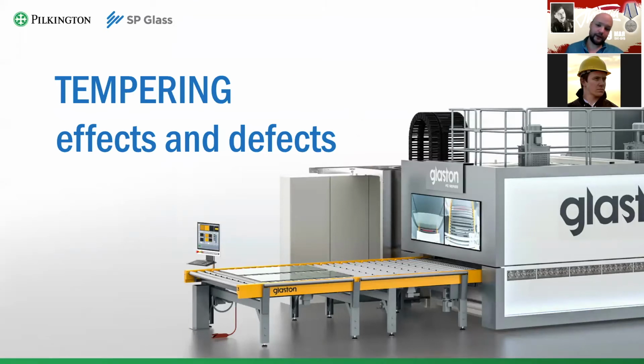So, what do we have in tempering? We have a heating section in the tempering furnace, and we have a cooling section. The thing is that in the heating section, glass is heated up to a point where it loses its elasticity. Under normal conditions, glass is a completely elastic material. We have a glass, we bend it with some force. When we remove the force, the glass will return to exactly the same shape it was before.